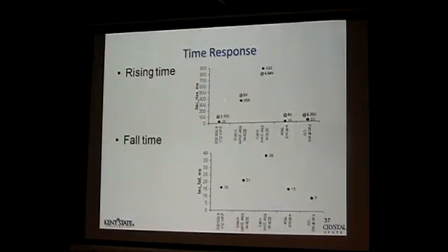But in the turn-off time, I think when some of the network grows longer and bigger, it costs some energy to reorient the liquid crystal, so it takes much longer. In other cases, you can see that the network is a kind of nanostructure, and it gives you much faster response. So what controls the turn-off time? The molecules have homeotropic alignment. You turn it on like this. When you turn the field off, they have to go back, right? They have to prevent back flow. And what kind of energy do you have to make them rotate or reorient back to the original state?